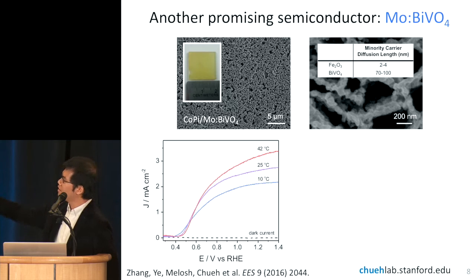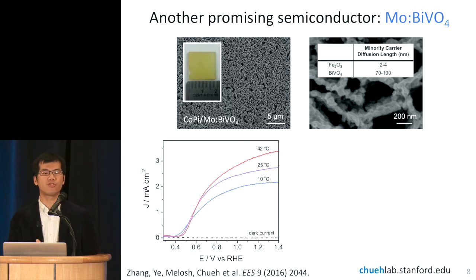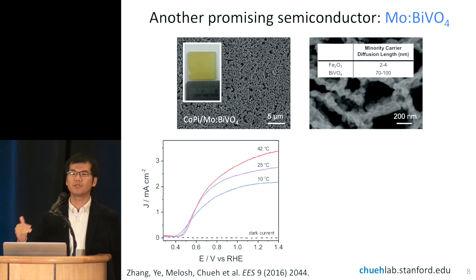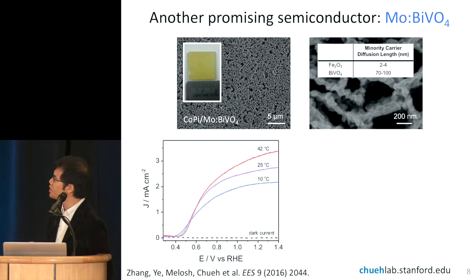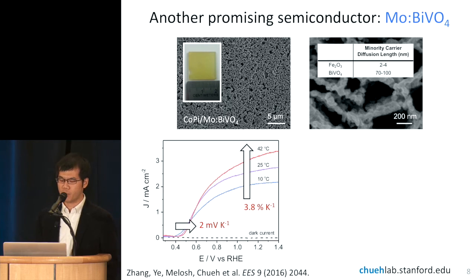These are the IV curves with and without light. Without light is the black dashed curve. With light are blue going to red. As we increase the temperature by just 32 degrees Celsius, we're able to increase the saturation photocurrent density from about 2 milliamps per centimeter squared to almost 3.5. If I plot this and show you the coefficients, now we're up to about 4% per Kelvin.